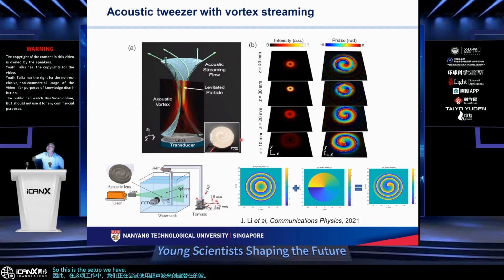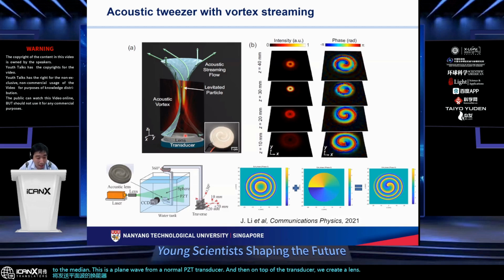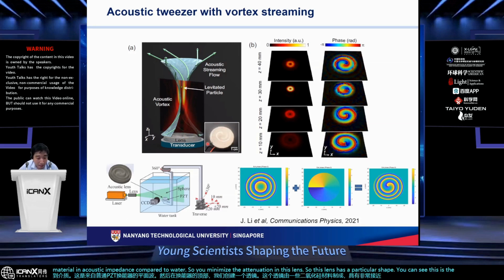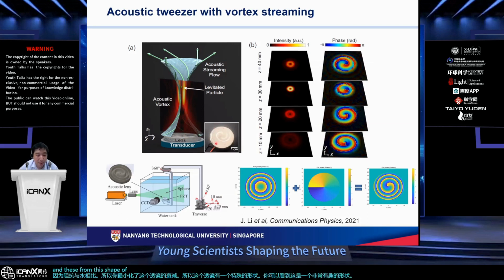We have the transducer, which will send a plane wave into the medium. This is a plane wave from a normal PZT transducer, and on top of the transducer, we create a lens. This lens is made of a silicone material that has acoustic impedance very close to water, so you minimize the attenuation in this lens. The lens has a particular shape. You can see it's quite a funny shape, and this shape will control the phase of the ultrasonic wave when it exits the lens.